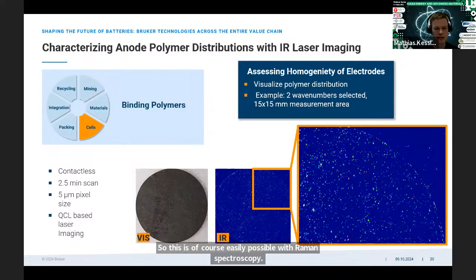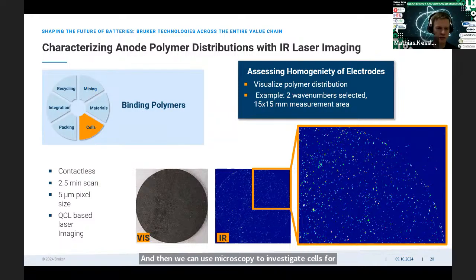Then we can use microscopy to investigate cells, for example, the anodes of a battery cell. If you use a laser IR microscope, then we are able to measure very fast, to scan the surfaces very rapidly, so we can then investigate such a graphite polymer mixed anode electrode, and then we can see the contribution of the polymer over the surface and have a representation of that very nicely with a very fast measurement. So this is done then in 2.5 minutes, and you have the image of the complete surface. So this is very useful for electrode investigations of batteries.